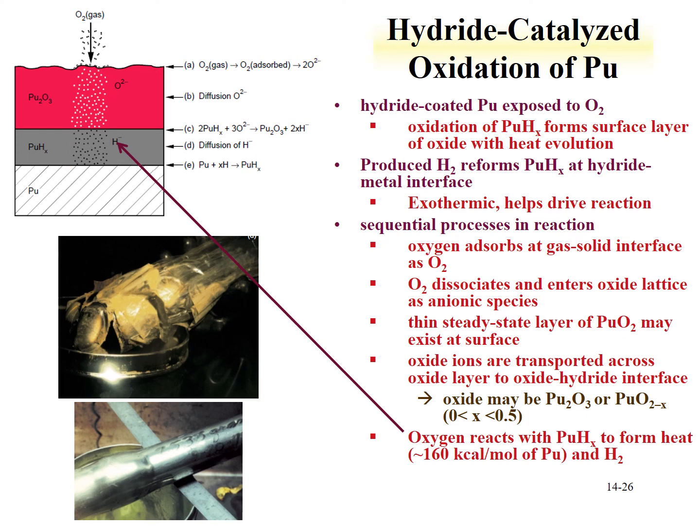Now, why this is important is that for storage of plutonium metal, you want to prevent any sort of oxidation from occurring, because it goes from a very dense material to a lighter material. That means you have swelling, as an example here, of 2 storage containers that contain plutonium metal. Upon the reaction of this oxidation reaction, the material converted from the metal to the oxide and the hydride, swelling the package, and in one case, bursting the package.